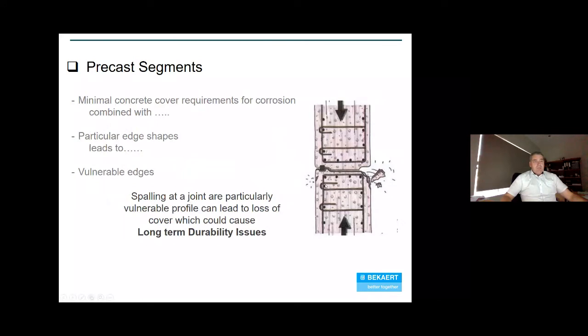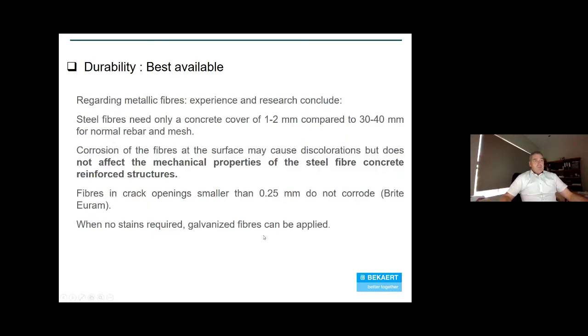I guess the biggest issue we have is the bursting of the unreinforced concrete section, which can affect your long-term durability of your reinforced cage. There's quite expensive to repair, and a lot of cost involved in that application. I guess durability is a very big issue, and it's something we address quite commonly. And with steel fibres, we don't need the cover that conventional reinforcement needs. We only need 1 to 2 millimetres compared to 30 to 40 millimetres of conventional rebar.